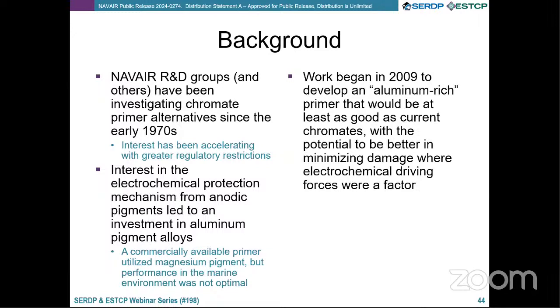But we evaluated it and found that it wasn't particularly optimized for the Navy environment, which is very corrosive, as you can imagine. And so my predecessors began work about 15 years ago to develop an anodically active primer that was hopefully as good as, if not better than, hexavalent chromium.